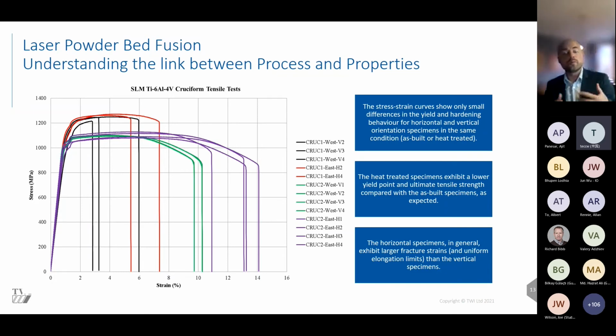And so this is why it's important to have not only the phase transformation kinetics, but also things like the solidification texture. And we can see once we take this AM material and give it a nice heat treatment, the purple and the green curves give us what we'd expect of Ti64.